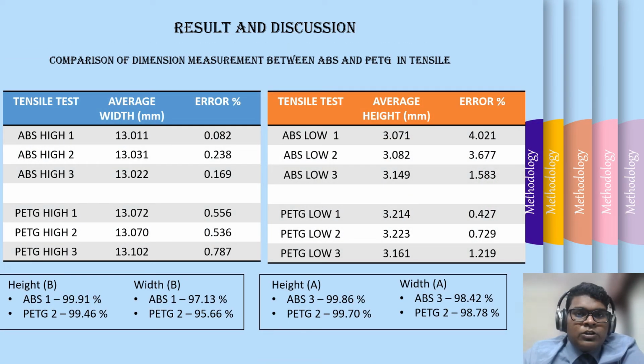By comparing the measurement of width of ABS and PETG in the high-level parameter, we found that ABS has the minimum error compared to PETG. By comparing the measurement of height of ABS and PETG in the low level, we found that PETG has the minimum error compared to ABS.